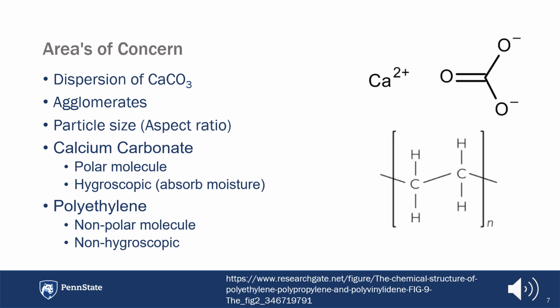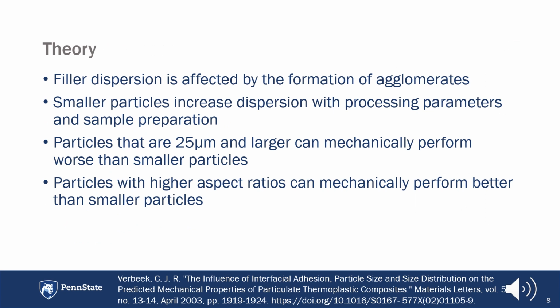And that's how we got a good dispersed testing materials for our project. So the theory behind this project: filler dispersion is affected by the formation of agglomerates. Smaller particles increase dispersion with processing parameters and sample preparation. Also from research, we found that particles that are 25 microns and larger can mechanically perform worse than smaller particles, and particles with higher aspect ratio can mechanically perform better than smaller particles because longer particles can transfer stress better.